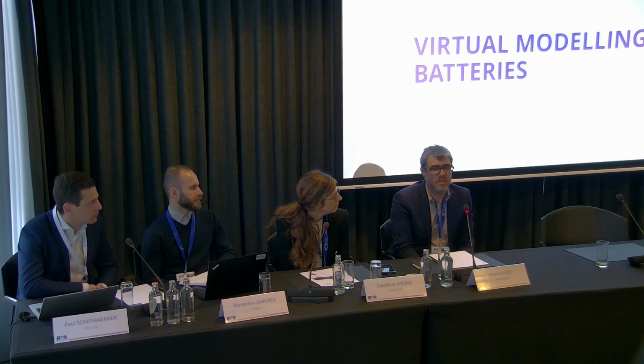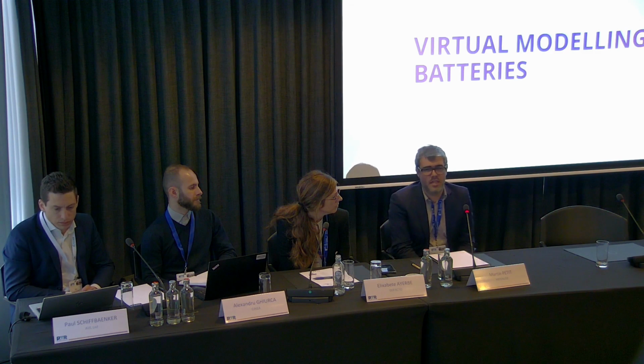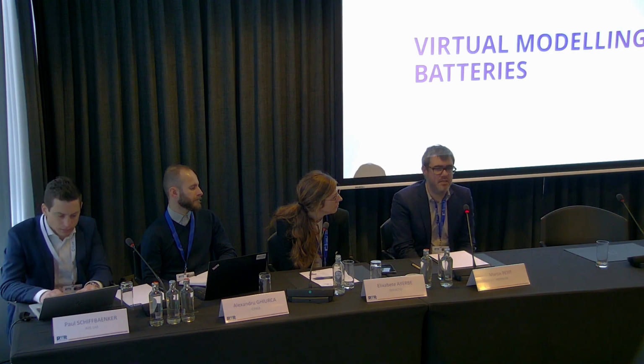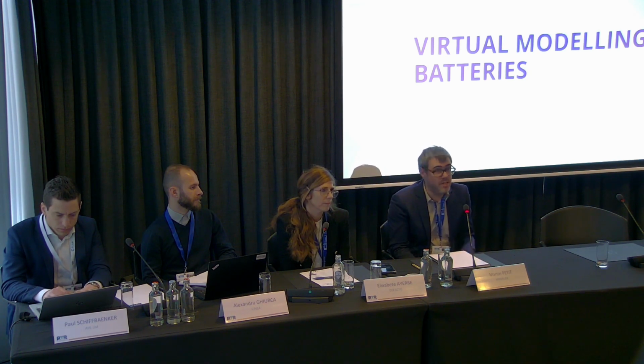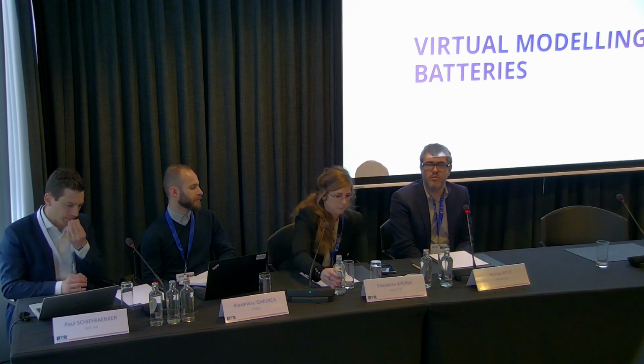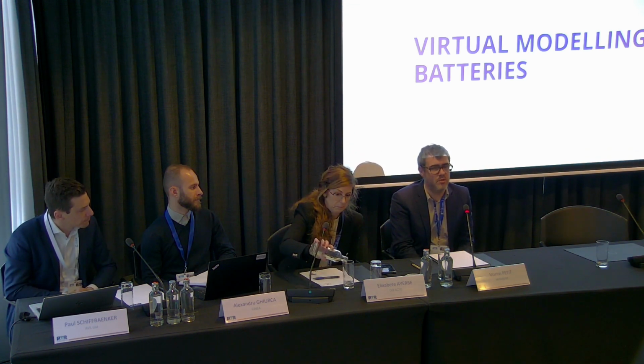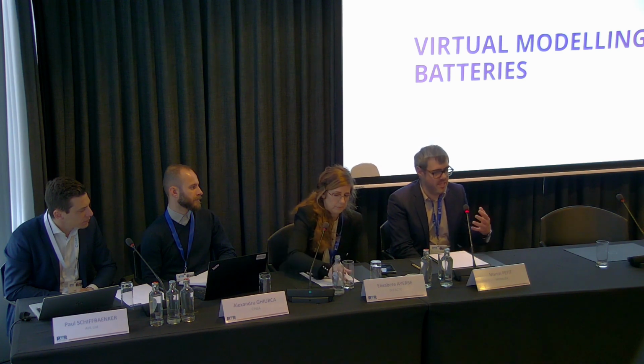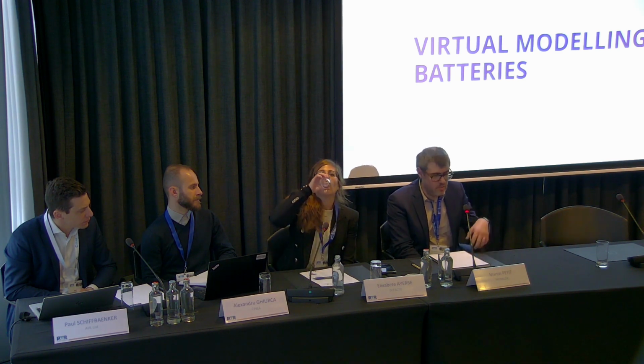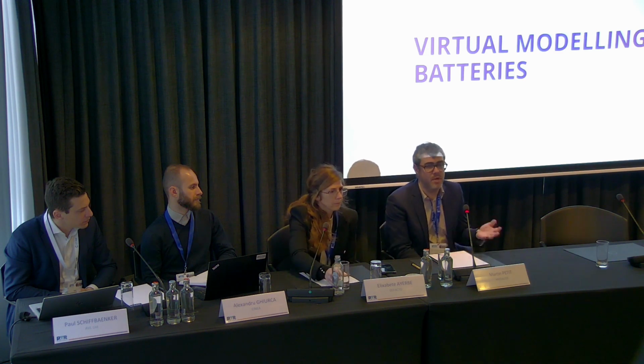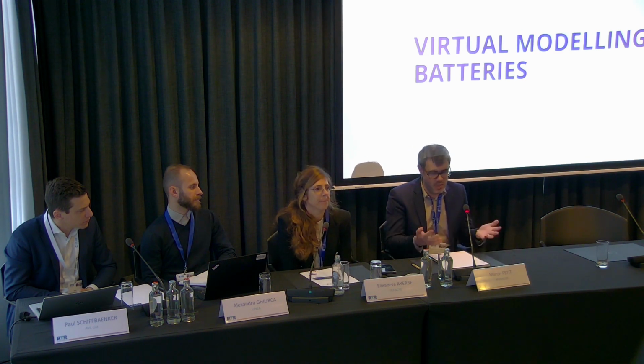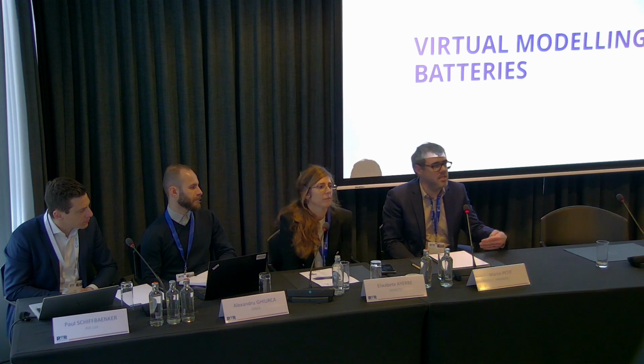So obviously when I began the modeling of batteries, we were focusing on electricity first, electrostatics, and then electrochemistry. Now we see that mechanics has a huge part to play, especially for lithium plating, for mechanics of the electrodes, for lithium with silicon, with lithium sulfur, and so on. So you need to take more and more mechanisms into account. It's more complicated, but the idea is to say, okay, we have this model that is working. We put this in with specific parameters that are fit for our applications, and now let's see what the impact of mechanics is. Is it negligible or not?